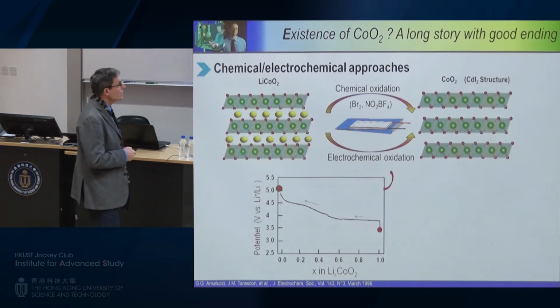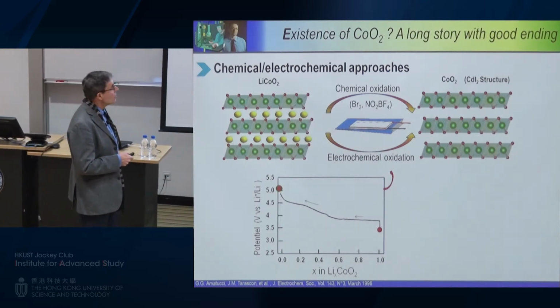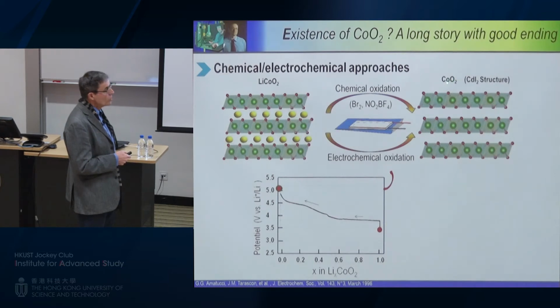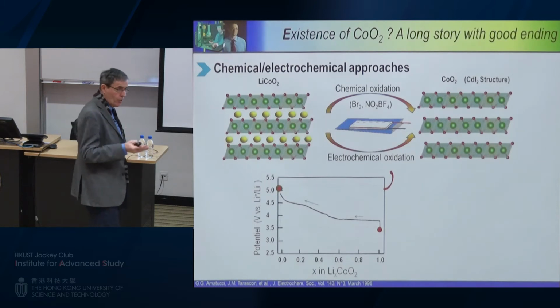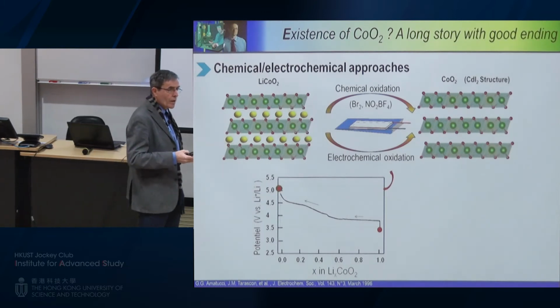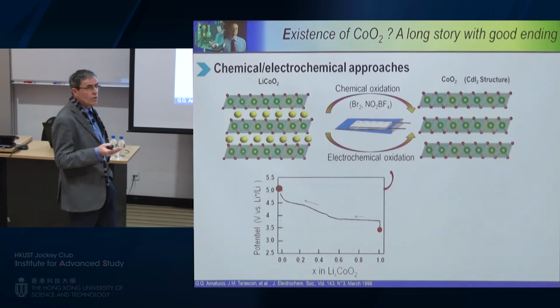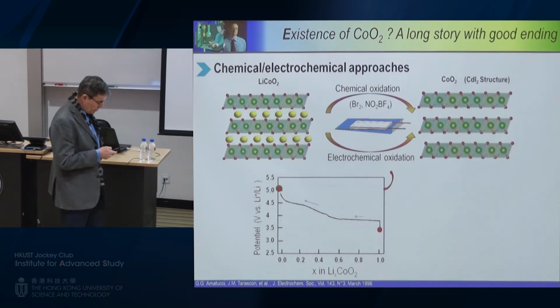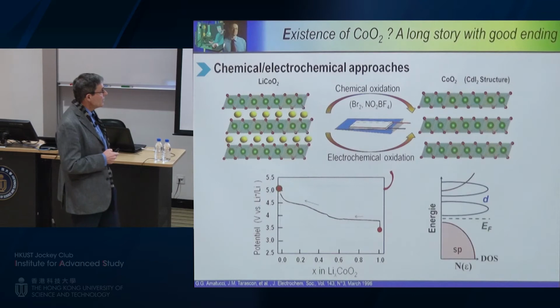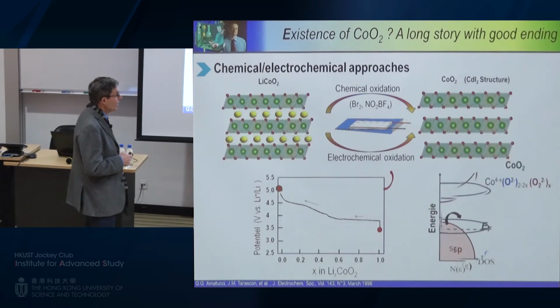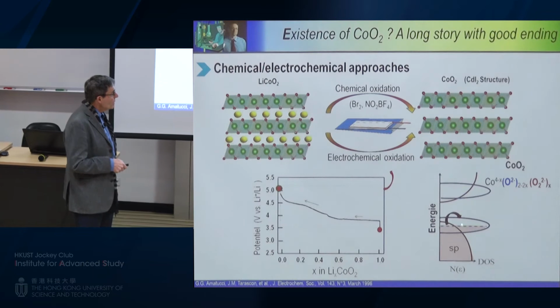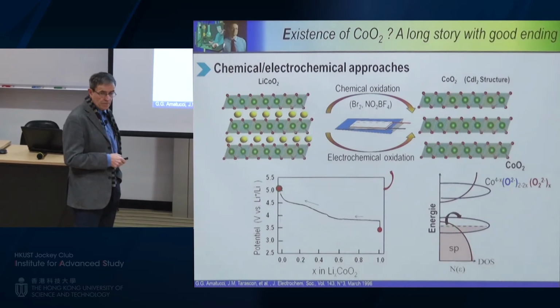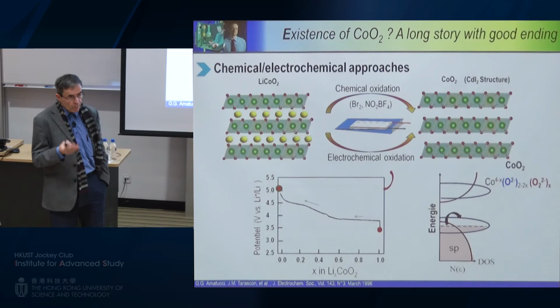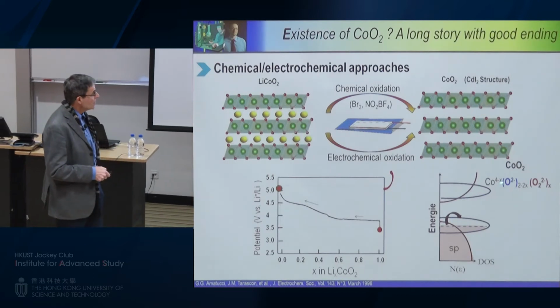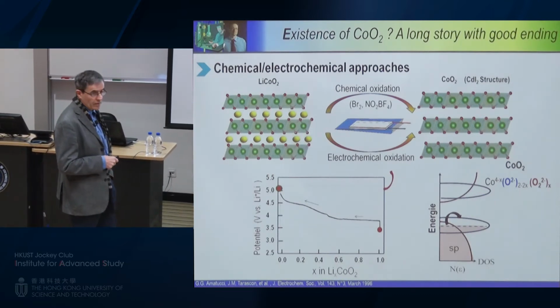And now the question is, what happened in this structure? If you do a simple calculation for CoO2, you realize that cobalt theoretically should be at the 4+ oxidation state. But when we were doing magnetic measurements, we could never obtain this. So, at the time, back in 1999, we proposed this model, in which we say that the ionic network should play a role here. And we should start to get electrons out of this band.